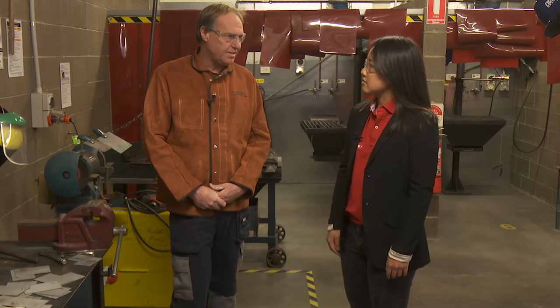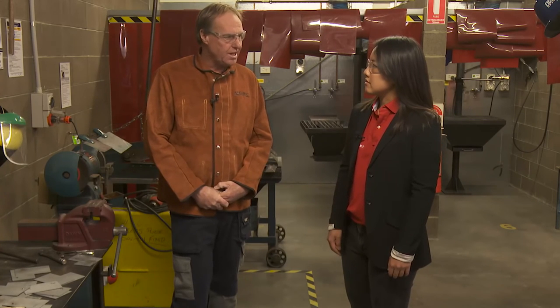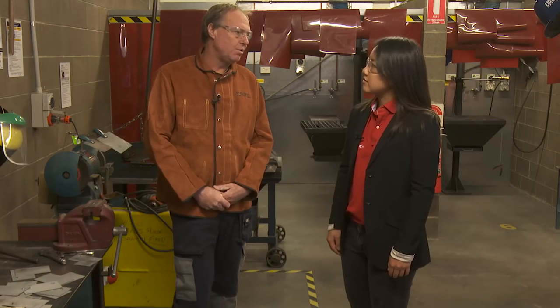MIG welding is when you're using an inert gas, and MAG welding is when you're using an active gas. So when we weld steel with steel wire, we're actually doing MAG welding, which uses an active gas, carbon dioxide mixed with argon. MIG welding is when we use an inert gas. So for steel welding, we're using an active gas. When we get into silicon bronze and aluminium welding, we're actually using an inert gas. So the MAG, the gas in it that's active, helps create extra heat in the weld zone.